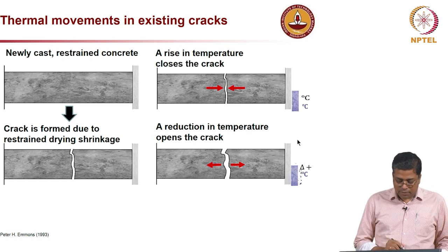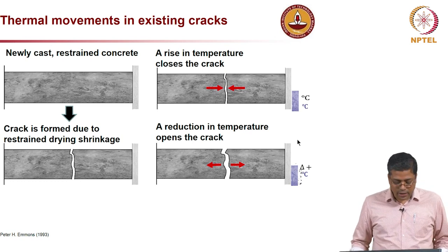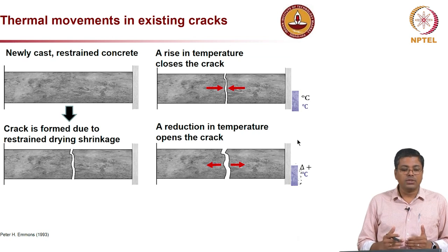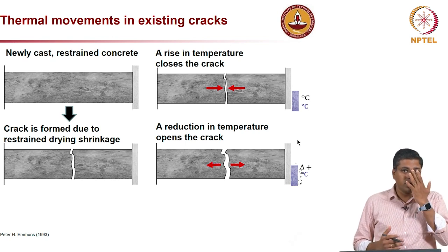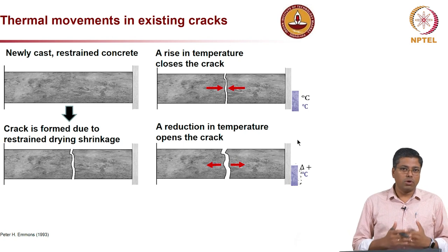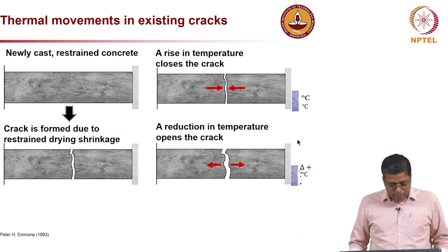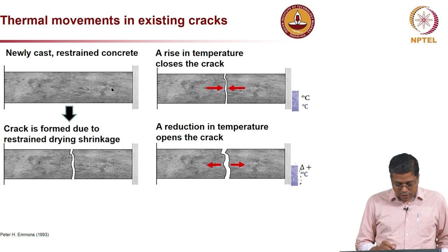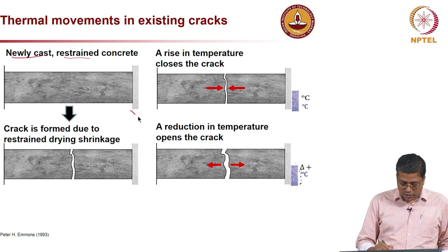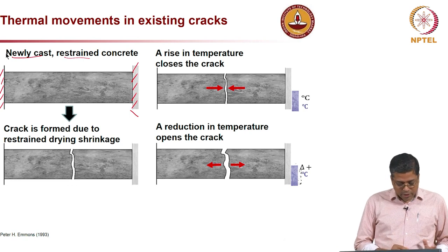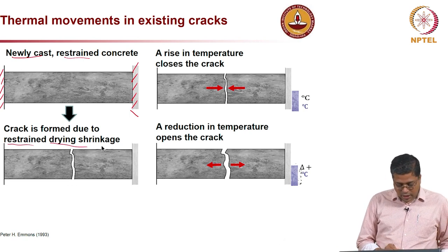Now, this is an example to show if there is already a crack, like I just mentioned earlier. Because of the temperature variations, this crack might close, open, close, open, all that might happen. So, in this particular example you can see on the top left image, it is a newly cast concrete with restraint on both sides. So, this side is fixed, this side is also fixed. So, what will happen? A crack is formed when restrained drying shrinkage happens.